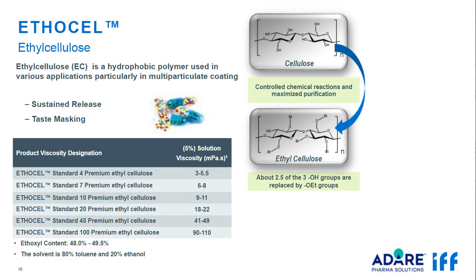Ethyl cellulose, with the trademark name of Ethocel, has been manufactured in Midland, Michigan for more than 80 years from cellulose. Through chemical reaction, cellulose is ethylated and converted to ethyl cellulose under tight control conditions, followed by purification processes. Viscosity of available grades of Ethocel is shown in this second table. We have a tight control over the degree of ethoxy substitution and solution viscosity. These two properties are the most critical variables in the final properties of any Ethocel grade.